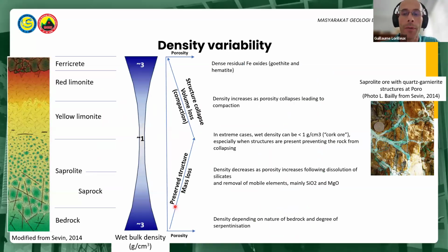The partial dissolution of peridotite generates a porosity which increases upward in the saprolite as the weathering is more advanced, leading to a decrease in wet bulk density from about 3 grams per cubic centimeter in the peridotite, depending on its characteristics, down to less than 1 gram per cubic centimeter in extreme cases in the upper saprolite. Such a low density ore is called minerai bouchon in French, in New Caledonia, which is called cork ore in English, and can occur when structures are present, preventing the rock from collapsing.